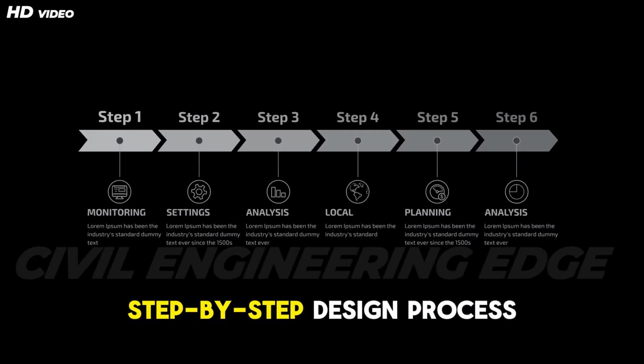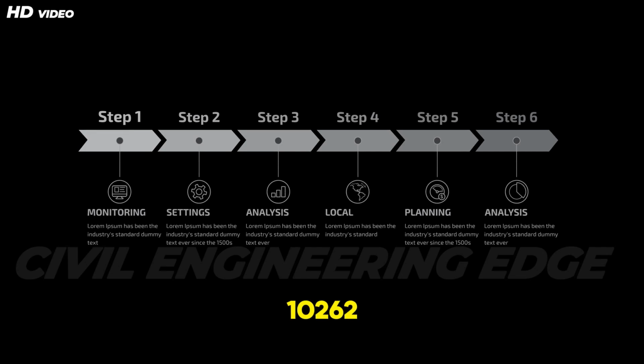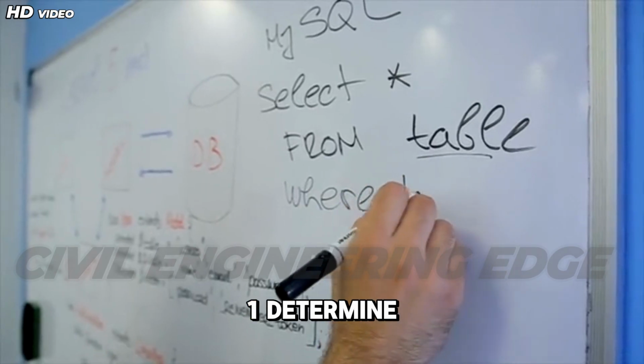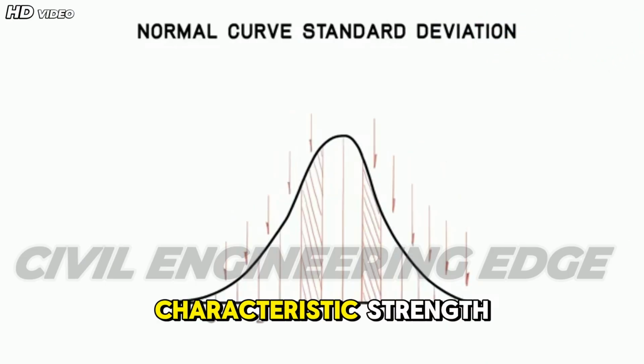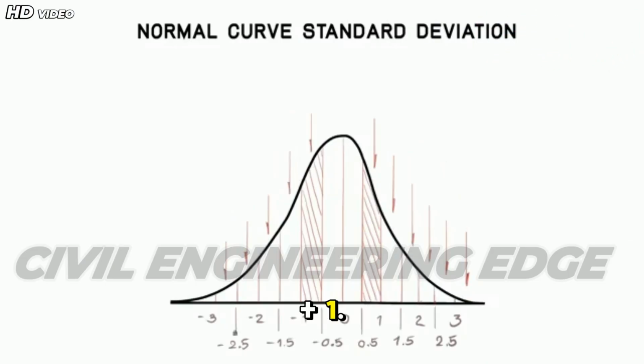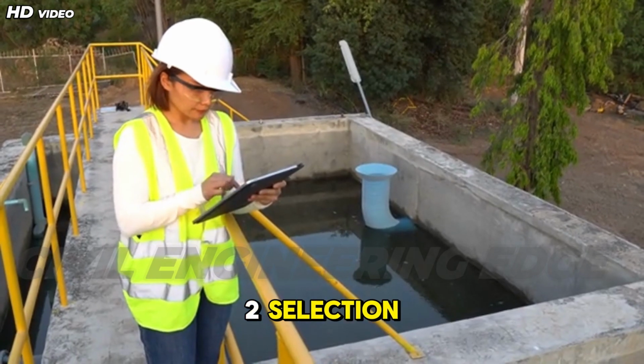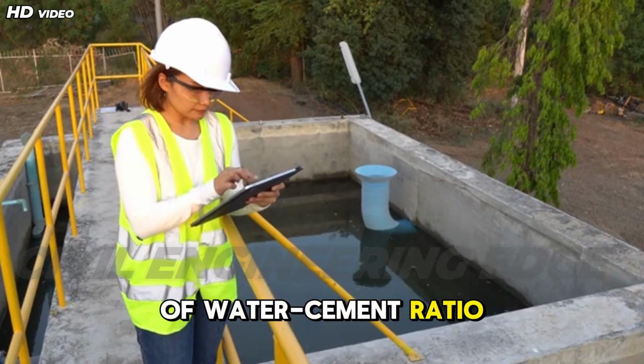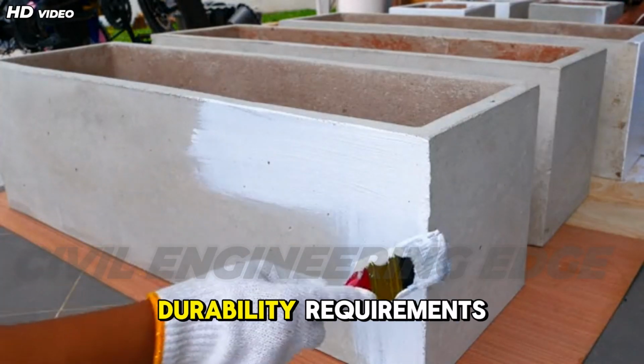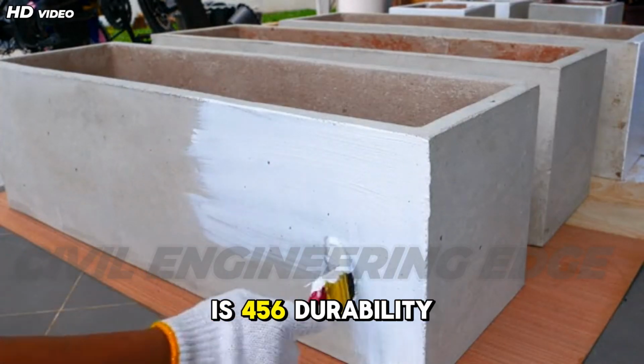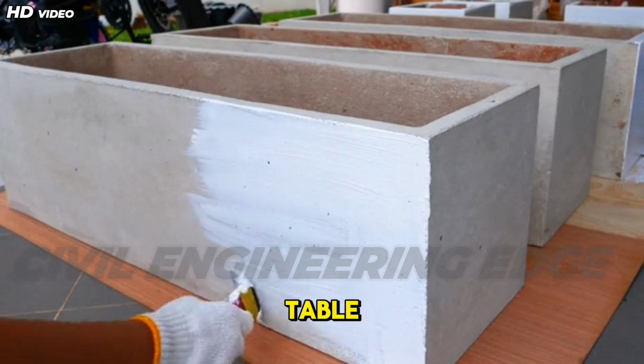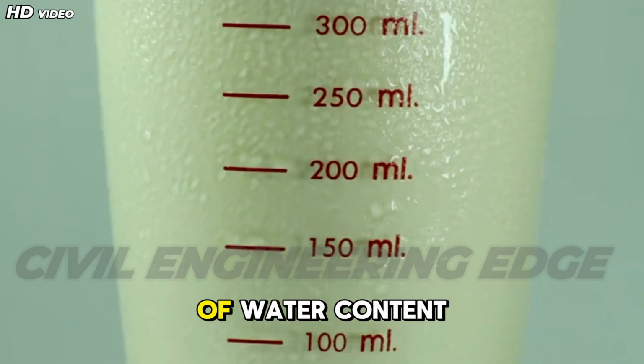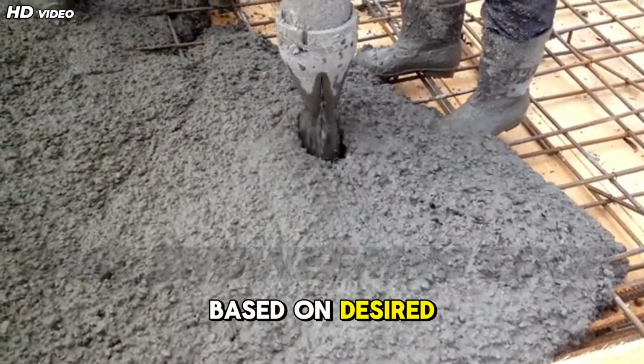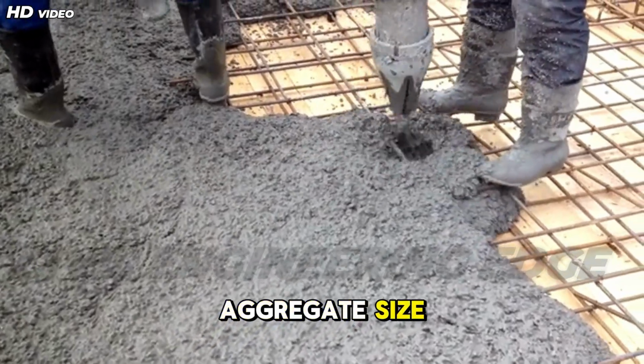Step-by-step design process as per IS 10262. 1. Determine target mean strength. Target strength equals characteristic strength plus 1.65 times standard deviation. 2. Selection of water-cement ratio, based on strength and durability requirements, IS 456 durability table. 3. Estimation of water content, based on desired slump and aggregate size.